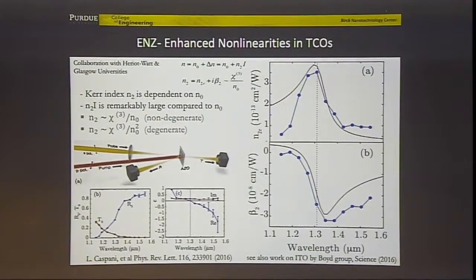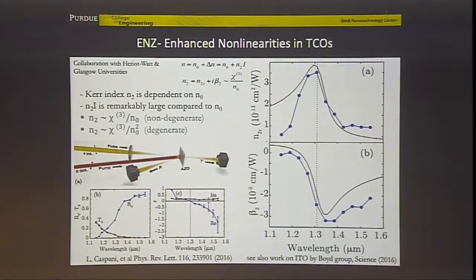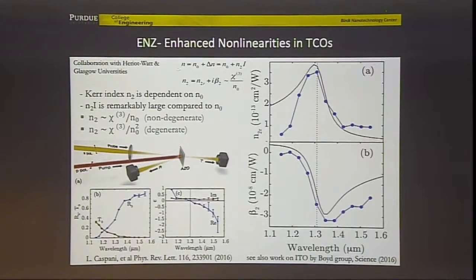If I slightly increase charge carrier density, my material becomes metal. If I slightly decrease it, it becomes dielectric. Clearly, I change optical properties dramatically, but it doesn't take much change in charge carrier density because I compare to the 0 point. So delta n, relative to n naught, the linear refractive index, is remarkably large here. It's actually unparalleled. And it's true not only for this particular effect, it's true about whole nonlinear responses. It's really like a new branch in nonlinear optics, which was enabled by these materials.